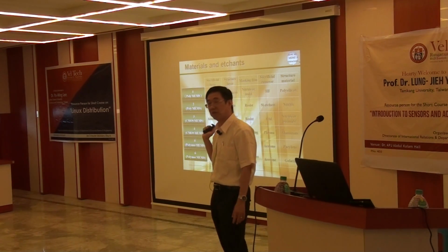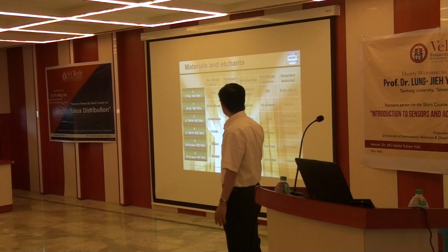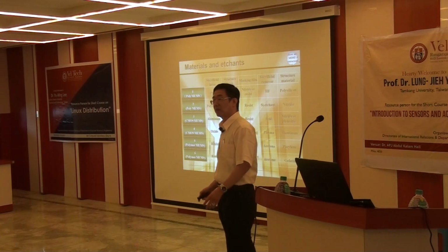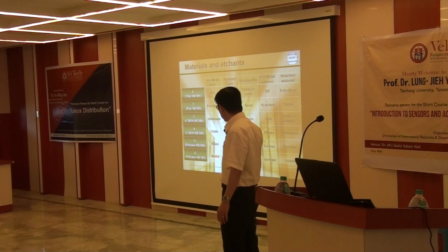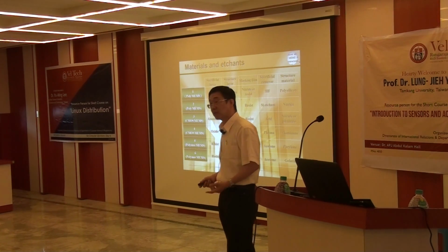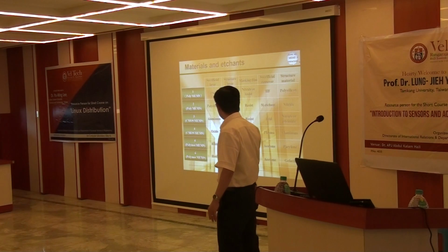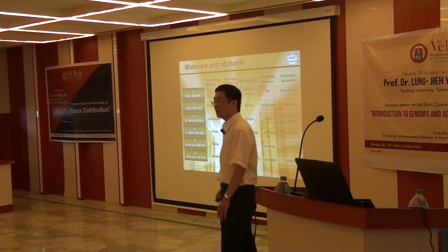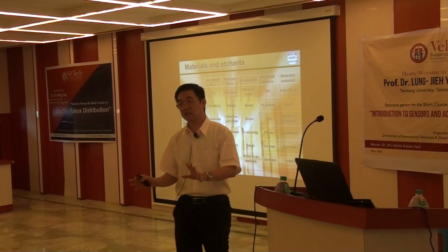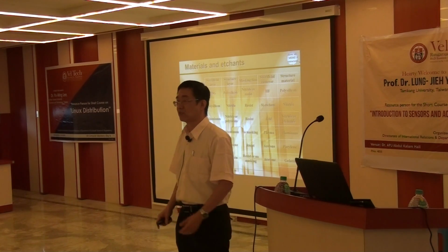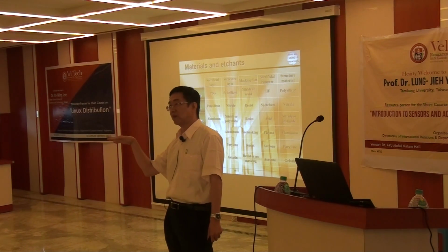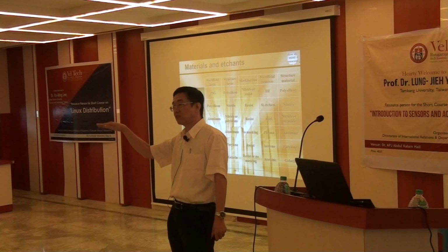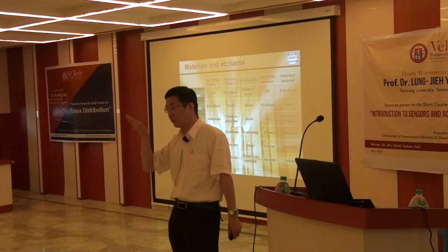We can do the gelatin structure, with photoresist as the sacrificial layer. And finally, we use acetone to remove the photoresist. But acetone will not attack parylene or gelatin. So this kind of polymer is preserved. So we have a parylene freestanding structure or a gelatin freestanding structure.